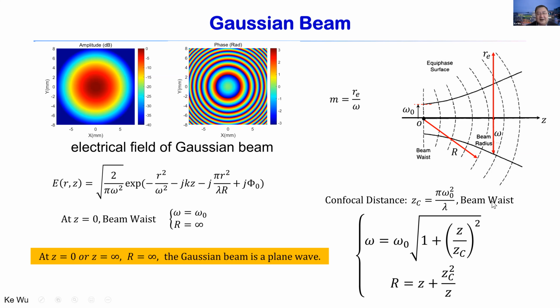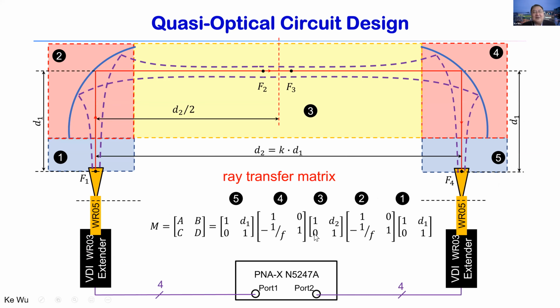So, for example, one of the problems in our measurement setup is that first of all, we need to create a very high quality Gaussian beam coming from the waveguide sections here. Usually the waveguide section provides normal horns, but normal horns cannot be used to generate high quality broadband Gaussian beams. So Gaussian beams should be generated by corrugated horns. Usually corrugated horns should be designed specifically for this kind of quasi-optic technique for a large bandwidth, because for the quasi-optic measurement technique, we need to pay attention to two aspects.